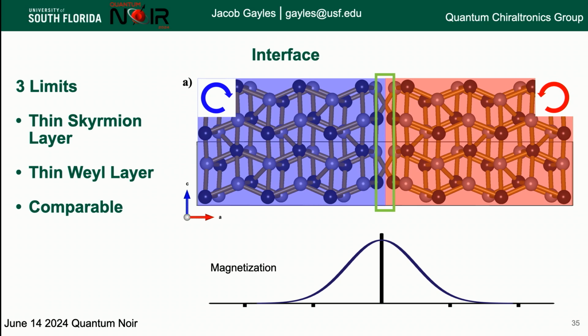So one thing that happens here is very interesting that we talked about earlier: if we take the cobalt germanium, pure, it has no magnetism in it. When we create this interface, there's actually a finite magnetism at the interface due to the breaking of the structure inversion symmetry you have there.